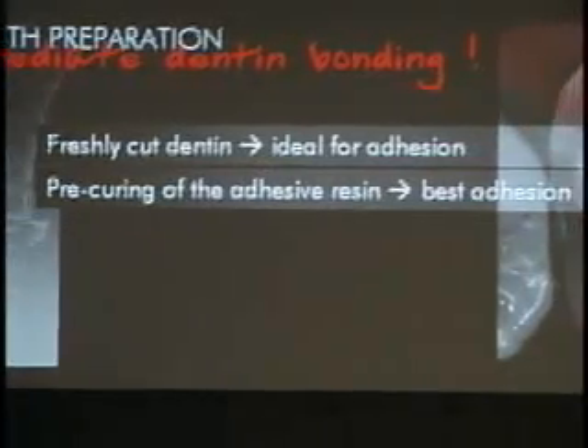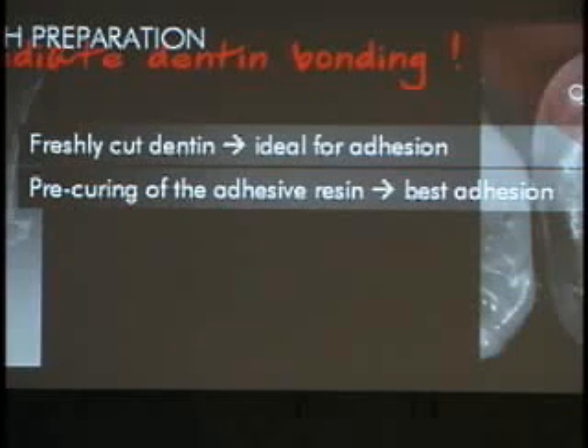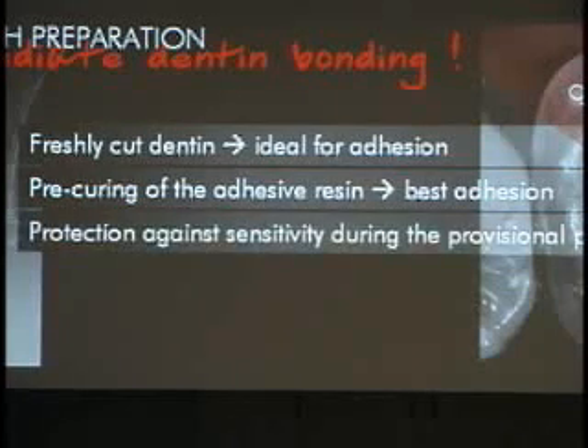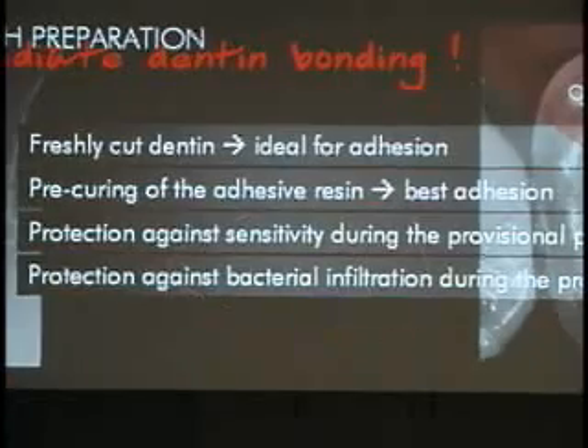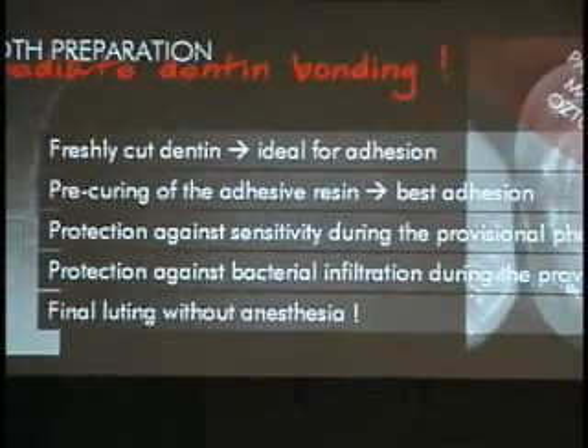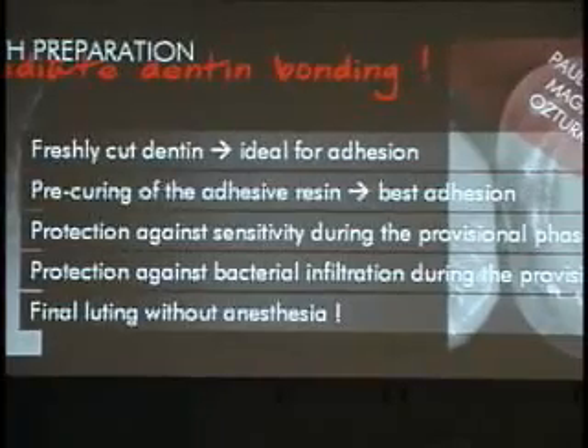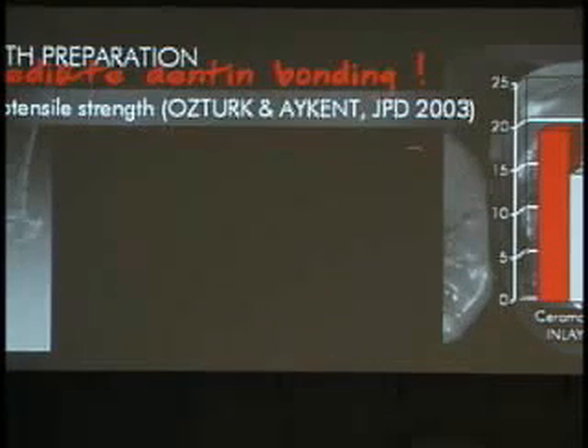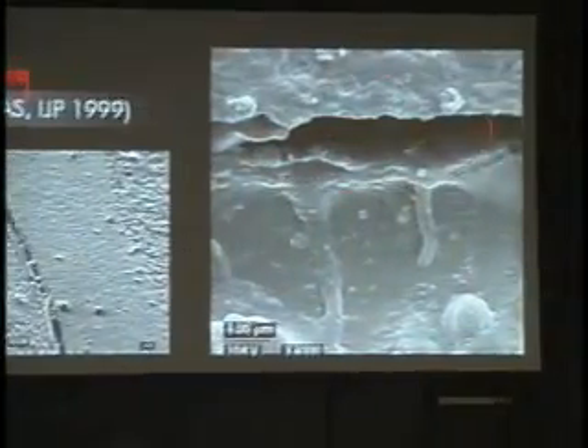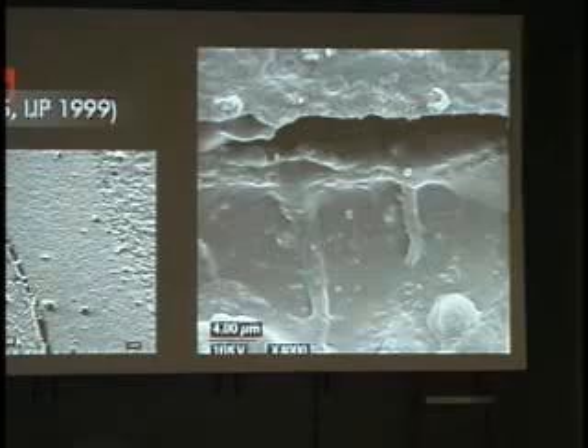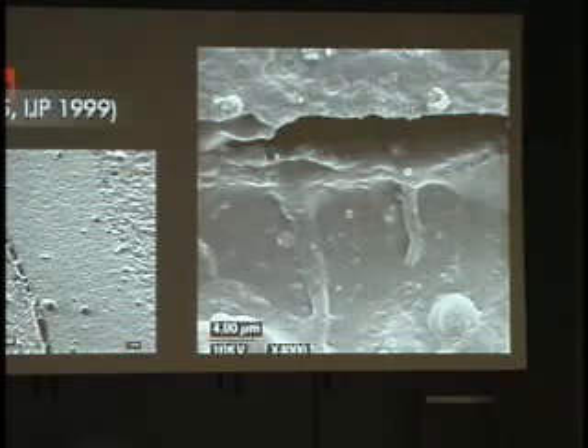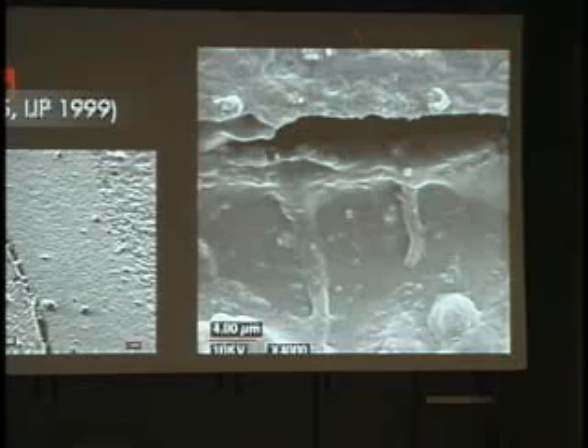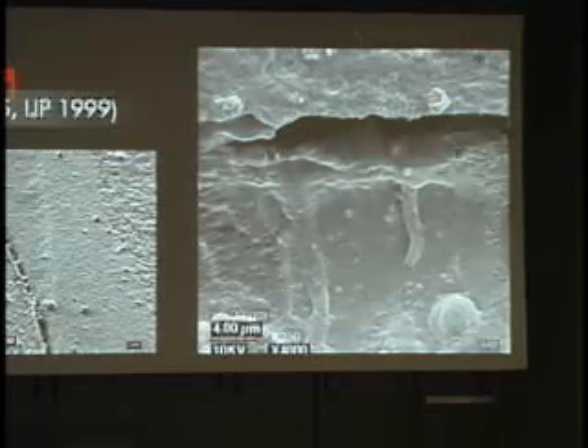But if you seal dentin at the time of final cementation, you are not allowed to cure the adhesive because the restoration will not seat otherwise. So it allows you to pre-cure the adhesive. It protects the dentin during the provisional stage from sensitivity, from bacterial infiltration, and the final bonding can be made without anesthesia because dentin is already sealed. So please seal dentin straight away when it's cut, before you take your impression. Studies show better bond strength to the sealed dentin, that's the red bars, and studies showed more cohesive interfacial aspect under scanning electron microscope. This is when dentin is not sealed immediately. The bond detached from the overlaying composite during polymerization shrinkage, and you lose bonding completely.